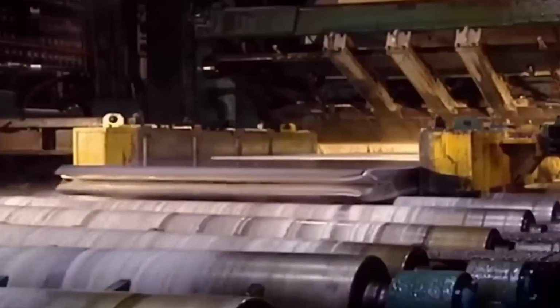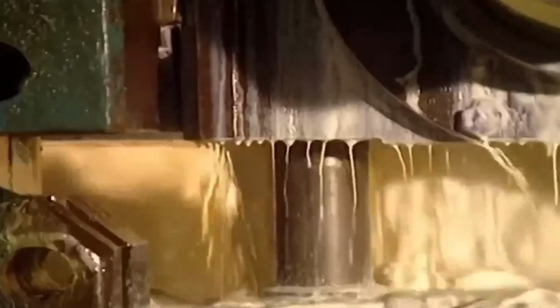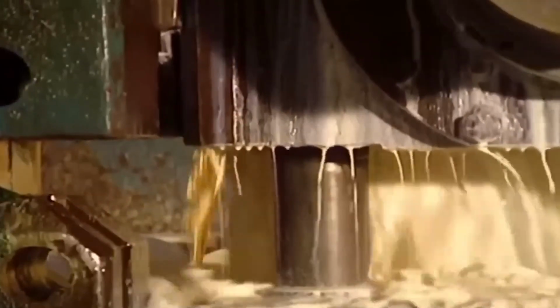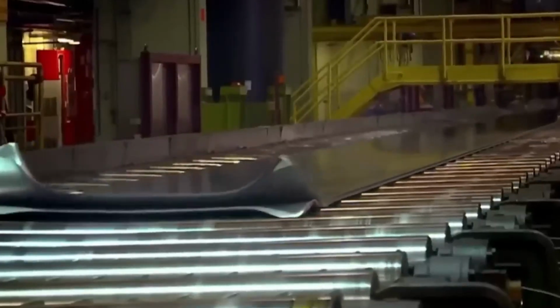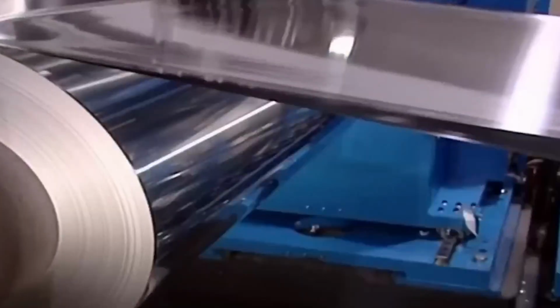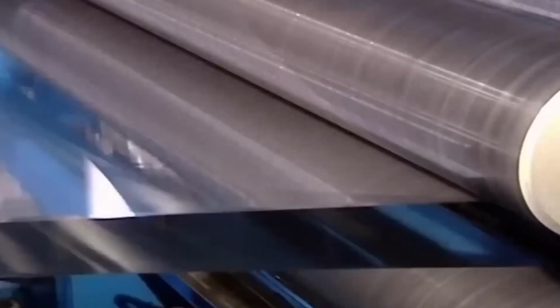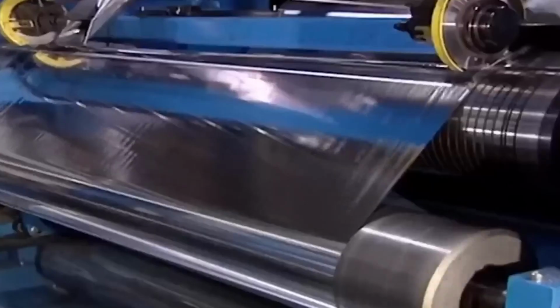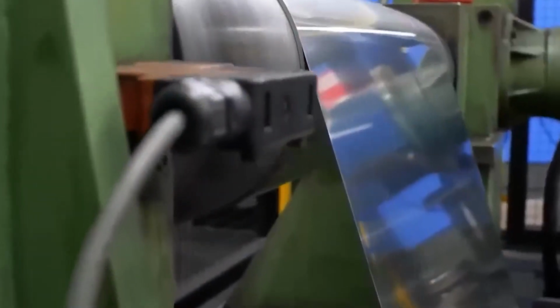The aluminum foil goes through final annealing and finishing procedures to improve its qualities and guarantee a constant thickness. After that, the large foil sheet is divided into rolls that are narrower. These are the typical commercial sizes for aluminum foil. The foil is subjected to stringent quality control inspections at every stage of production to ensure that it meets the necessary standards for thickness, tensile strength, and surface finish. Weighing and measuring a sample to find its area, then dividing the weight by the product of the area and the alloy density yields the thickness.